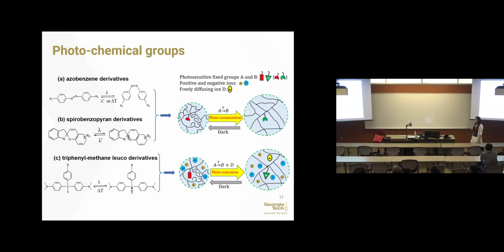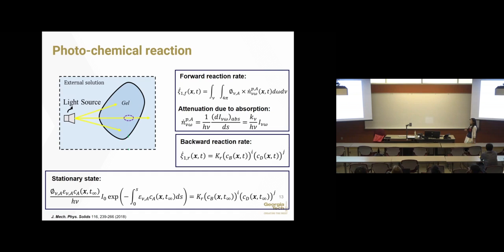So in the following modeling, I want to focus on this material system, and the model can be further simplified to cover other cases as well. So when the light propagates through the material a certain distance, and the light is consumed for generating this chemical reaction, the forward reaction rate is proportional to the number of photons that are absorbed by the material. And we also have a naturally thermal activated backward reaction. If we equate the forward reaction and the backward reaction, we get a stationary state.